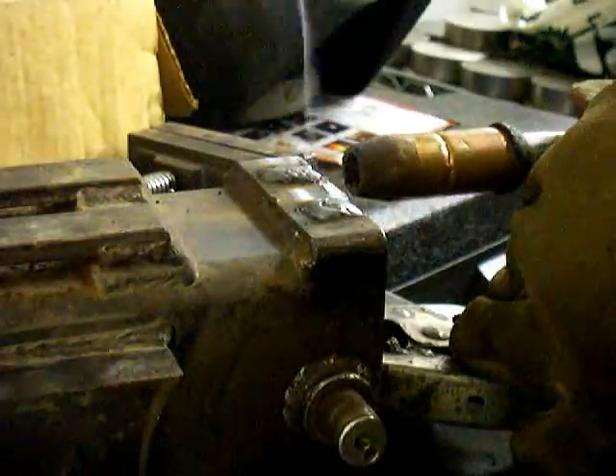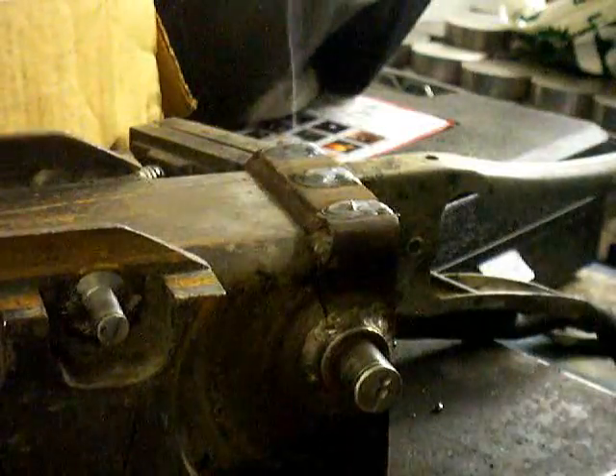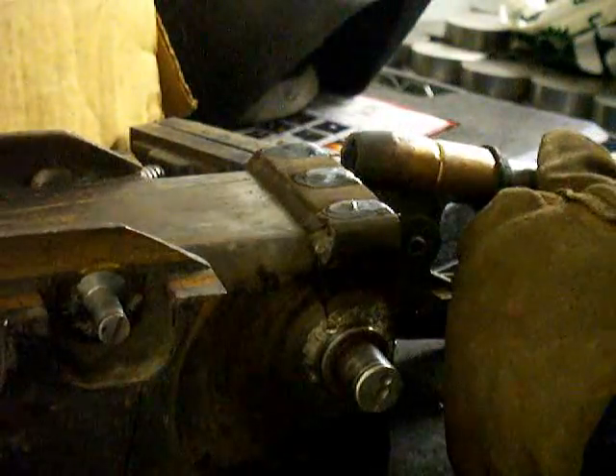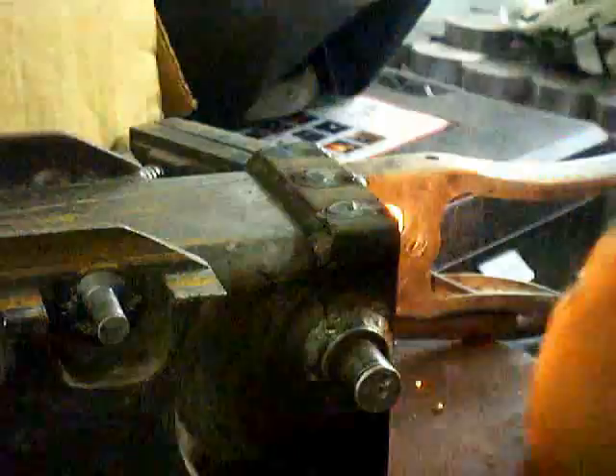There were five holes here total. Fortunately the machinist hogged them out for me, so all I've got to worry about is putting a good sound weld metal in there with enough of it. After I'm done with the bulk of it I do some touch-up on the ends and corners. I'm using a Miller Matic 250, probably about 19 volts and between 200 and 230 inches per minute of wire, 75/25 argon CO2 gas — just normal stuff, nothing fancy.